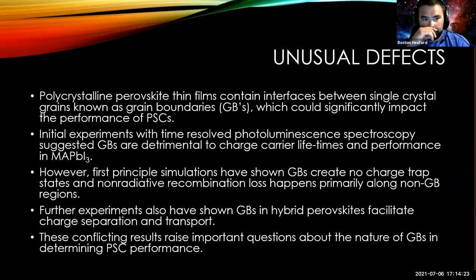And so those were all talking about just point defects in the perovskite systems. There are many other kinds of defects. One of the other kinds of defects that were explored were grain boundaries. And so initial experiments suggested that grain boundaries are detrimental to the charge carrier lifetimes in methylammonium lead iodide. However, a lot of first principles simulations have shown that grain boundaries create no charge trap states and that the non-radiative recombination happens primarily along the non-grain boundary regions.